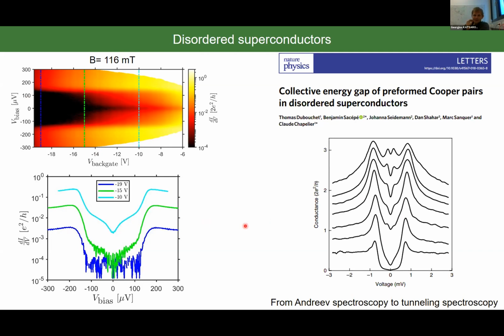What we found in the literature is that for disordered superconductors, which I show here on the right side, the group of Claude Chapelier in Grenoble has done tunneling spectroscopy by means of STM. They seem to see a similar dip. So the heavy speculation is whether, while we do etching, we create disorder in the aluminum. But as I say, take this as a heavy speculation. I would be happy if a theorist could provide me with an answer.